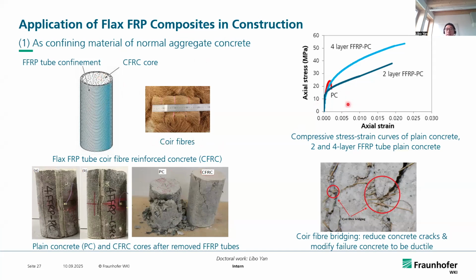In this stress and strain curve, we can see that compared with plain concrete, the use of 2-layer and 4-layer flax FRP is able to increase the load carrying capacity and the energy absorption capacity significantly.